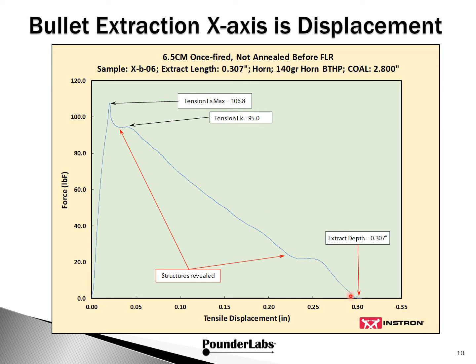And then we continue all the way down and get the extraction depth of 307 mils, which actually aligned perfectly with the seating depth we discovered on the seating part of the test. Now we notice that structures evolve, that we see a structure here when the bullet went in. There was some burnishing maybe on that going in. Now that we're pulling it out, the leading edge of the bearing surface might be burnishing some here.